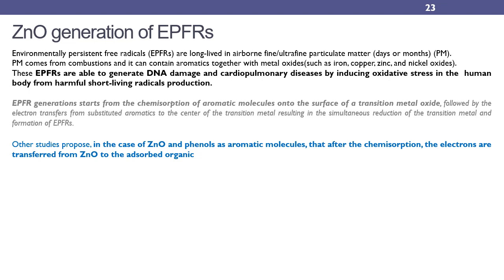The comprehension of the generation of these very stable radicals through the interaction of aromatic molecules and metal oxides is still under debate. Especially in the case of zinc oxide nanoparticles and phenols as aromatic molecules, it is known that the generated radicals are the most stable in the atmospheres, up to 73 days.